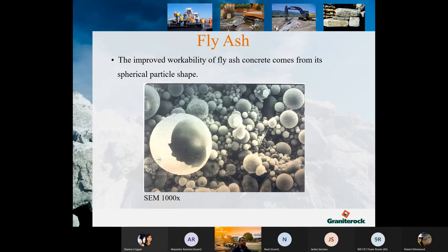Here's a little close-up of cement particles. And the reason why fly ash helps with workability is the particle shape. They're shaped like mini ball bearings. So when you're finishing the concrete, you'll feel that it's a bit smooth or creamy on top.